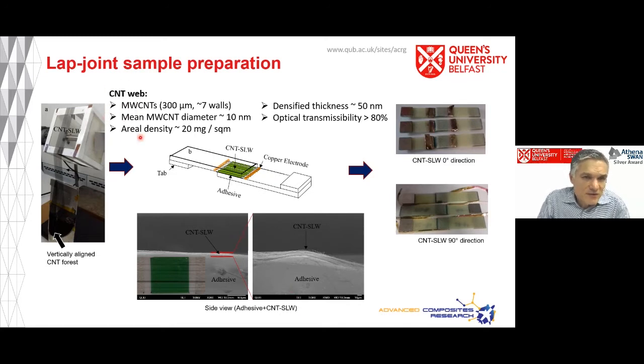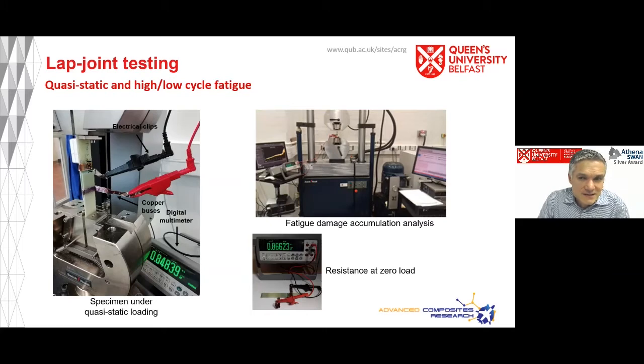This is some information on the carbon nanotube web, which I mentioned earlier. Probably what I didn't mention was the web is made out of multi-walled carbon nanotubes, about 300 microns long and about 7 walls, with a mean diameter of about 10 nanometers. What we did here was to put a single web at a joint, and then wanted to find out how well it can behave as a strain and damage sensor. So there's our setup.